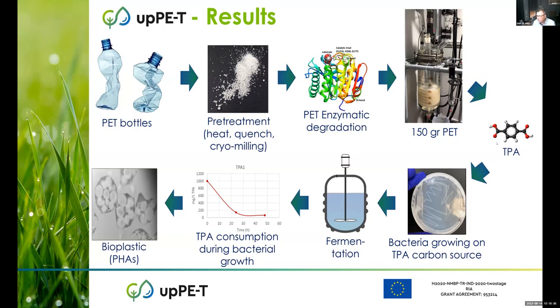And this is the structure of the terephthalic acid. We then feed the terephthalic acid to a bacterium called Comamonas that can grow on this type of molecule. And so we have a really very big fat growth of organism. We can see, for instance, in those fermentations that the level of terephthalic acid goes down over time. So we have evidence that the growth is due to the terephthalic acid that is present.